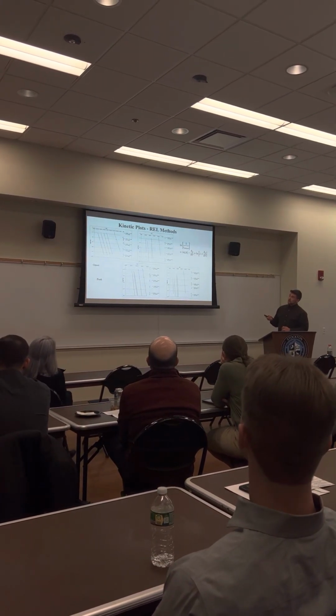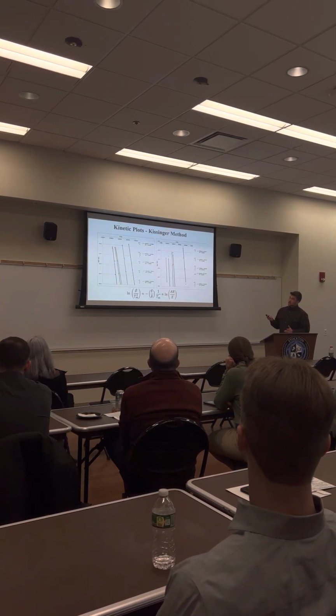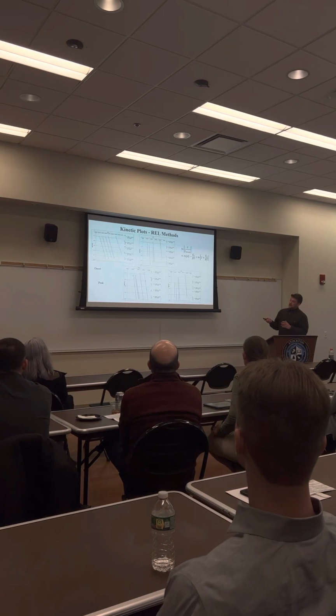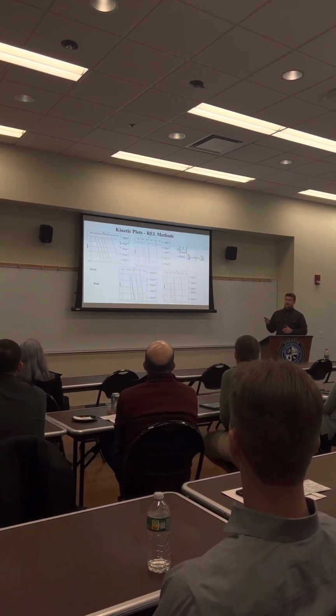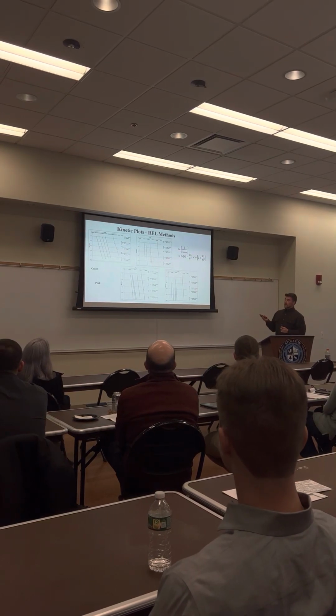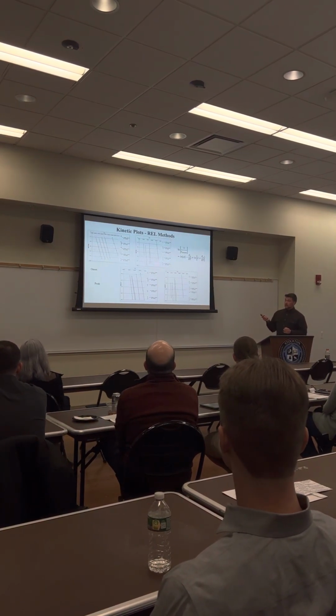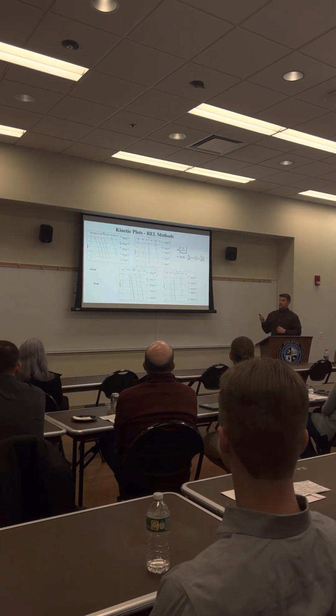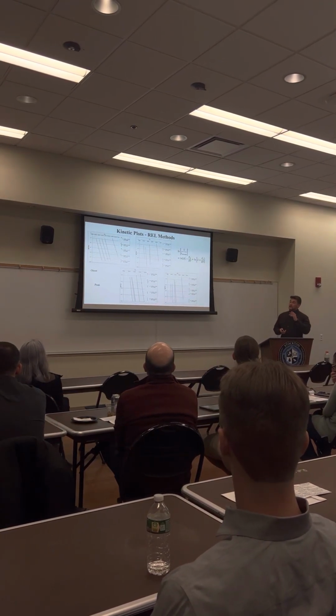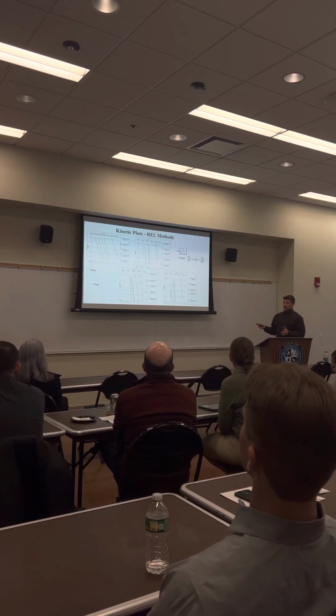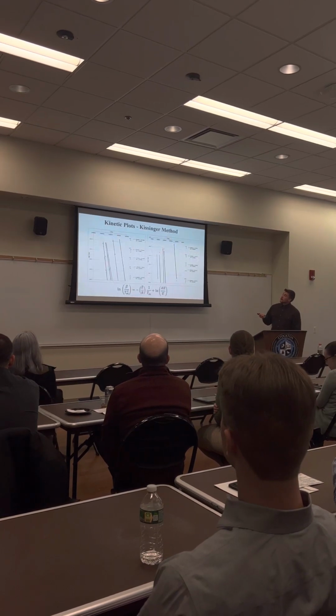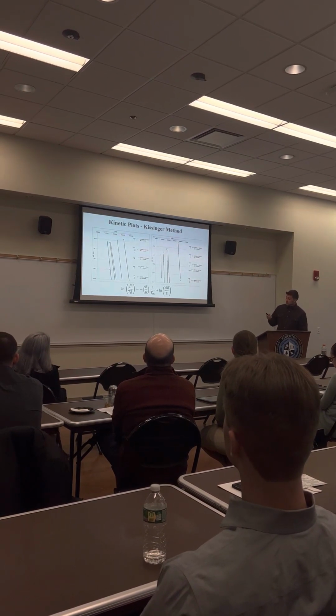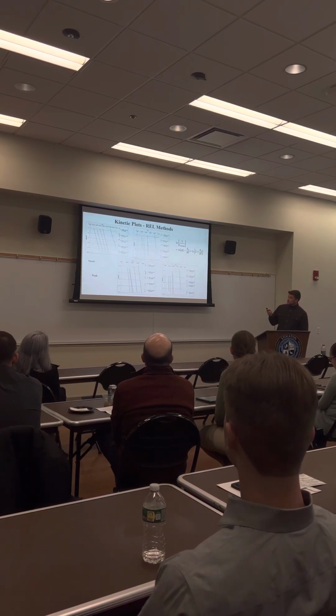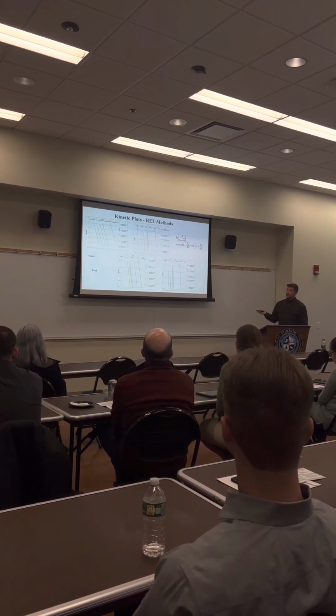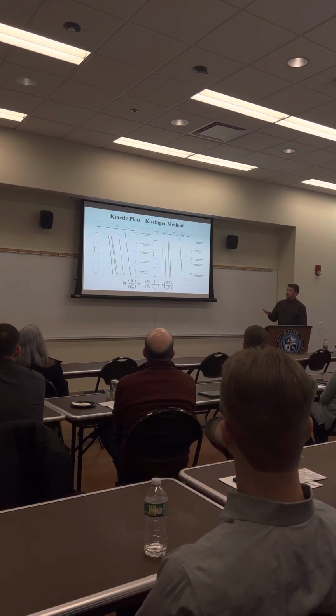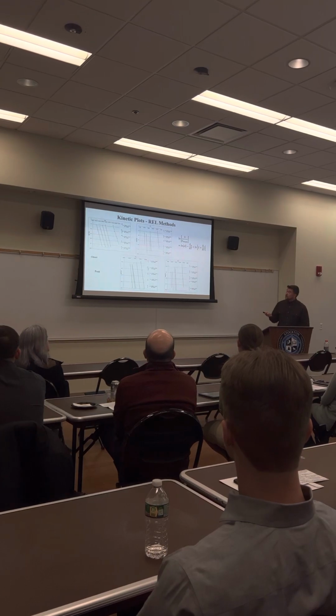These are the other onset temperatures. These are the same graphs, but with different extrapolations done for different factors. So we had these two methods. We applied the Kissinger method, which took advantage of the peak temperature values, and then we attempted to take the onset temperature values and get a different set of kinetic parameters. Going back, this was the equation used for these. You guys saw this? And then this is the other equation. They're both the same, they do the same thing, but this is just easier to represent all of the graphs.